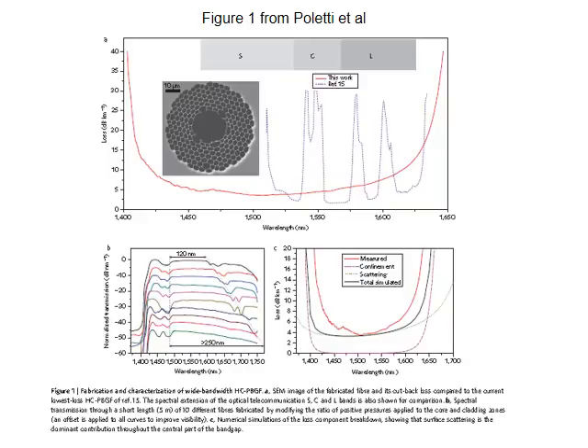This is a figure from the paper. At the top, the image shows the cross-section of the PBG photonic bandgap fiber. The hollow core is easily seen. Together with this image, authors show the cutback loss of their fiber in red in comparison with the best results from literature in blue. The spectral extension of the optical telecommunications S, C, and L bands is also shown.